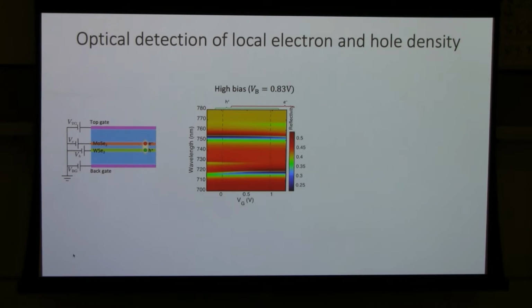Okay, with that in mind, if we have only a hole-doped layer or only an electron-doped layer, we have a one-to-one correspondence from optical spectrum to carrier density. So the idea now is, if we have bilayers where both electrons and holes are doped at the same time, can we use the same mapping to determine electron and hole density by looking at the spectrum? Here I show the experimental spectrum when you apply a large enough vertical electric field and large enough bias. In the middle region, electrons and holes are simultaneously doped.